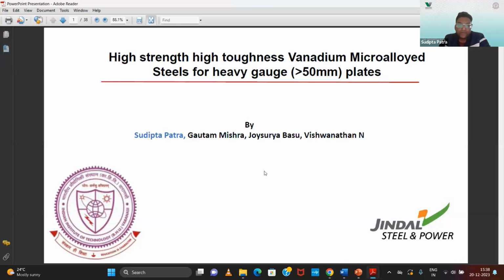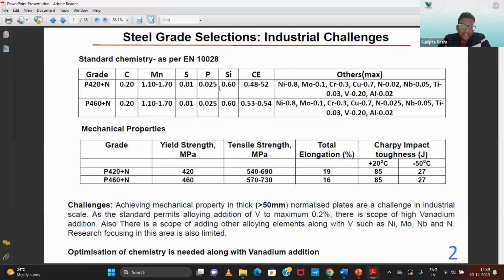Yes. So we are doing this project for the last 1.5 years, say. So we are trying to develop high strength, high toughness vanadium microalloy steel for a heavy gauge plate, especially greater than 50 thickness plate, with Jindal Steel and Power, our industrial partner. So basically, the problem of these grades is in high thickness. It is very difficult to achieve the mechanical property at greater than 50 thickness.